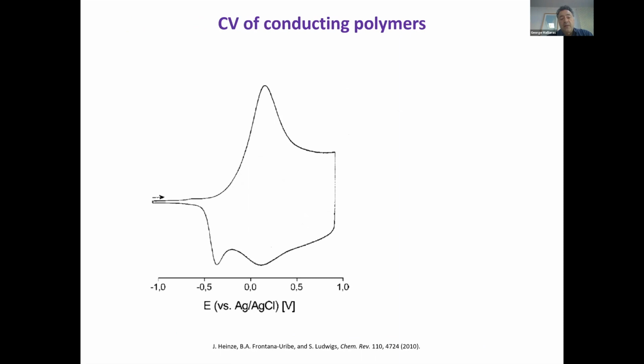Now, this was the case for simple metal electrodes. When you slap a semiconducting or conducting polymer, a conjugated polymer, on the metal, then the situation becomes much more complex. This is a CV, a cyclic voltammogram, of a conjugated polymer on a metal surface. And you see that it has peaks that you would assign to a Faradaic response, but also has this plateau here that you would be tempted to assign to a capacitive response.